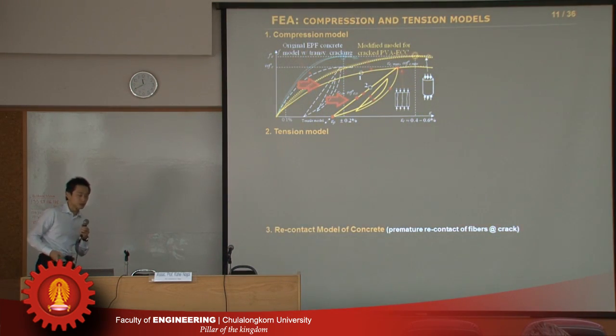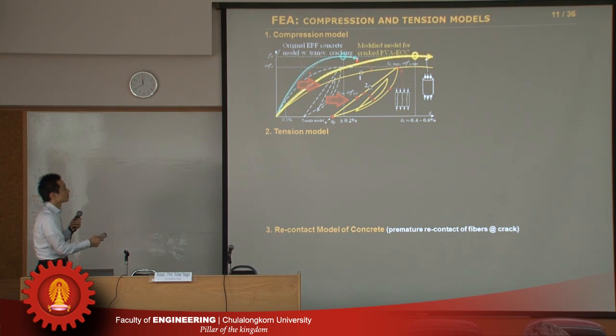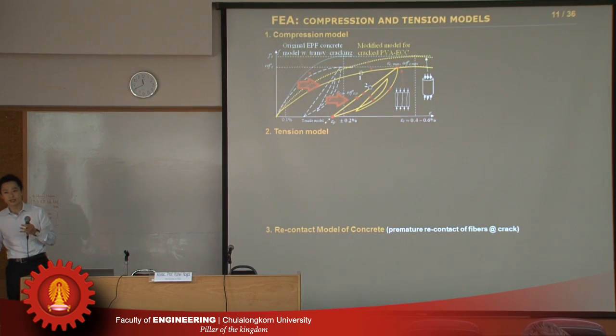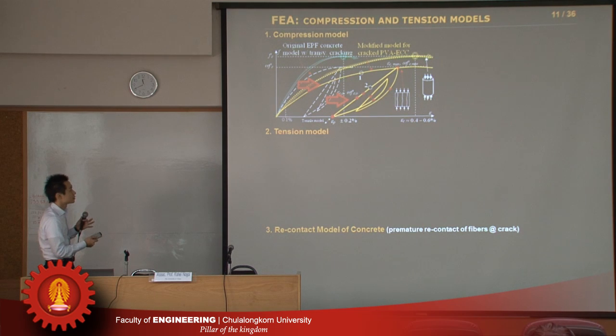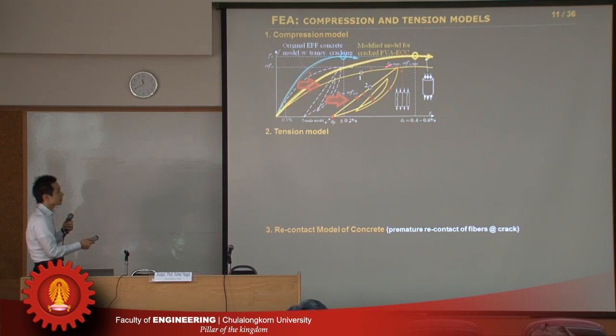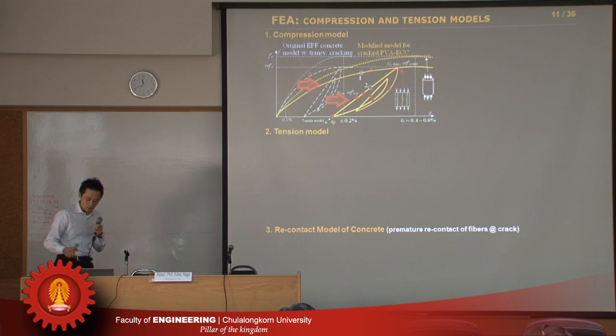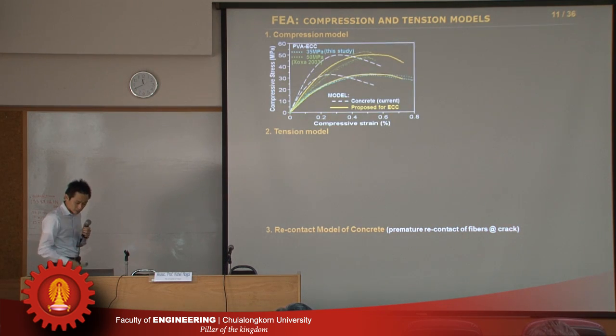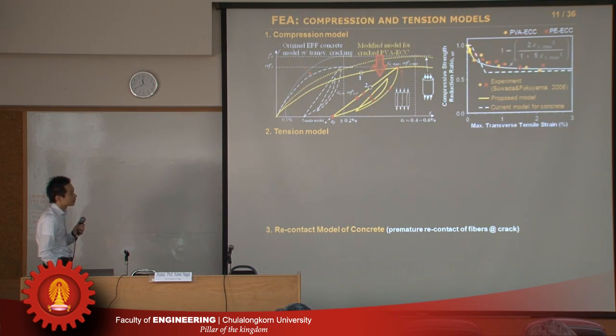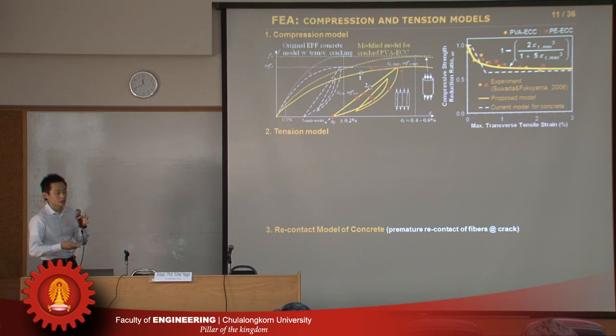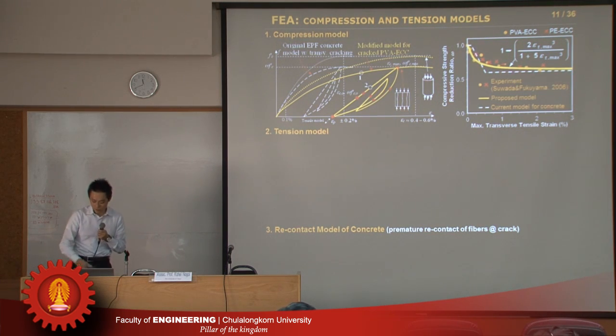So firstly, in compression. For compression, it's not so difficult. This is the original COM3 model, but it is known that HPLCC or ECC used in this study shows less stiffness and a higher peak strain. So based on the experiment, we modify it, and the same unloading reloading curve is adopted. Yes, in compression, the modeling is not so complex, and we checked the model, and compared with the experiment, it's okay. And also, due to lateral damage, in compression we also have some reduction of the strength. So this model uses some previous research. Anyway, a similar concept is adopted.